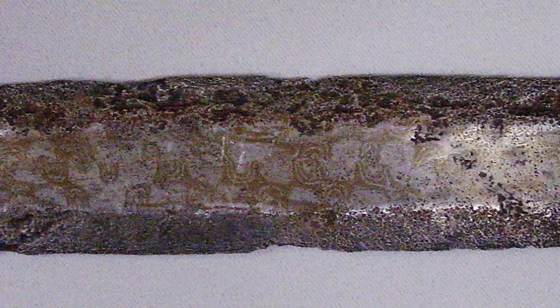It now resembles the original blade. At one point in modern times, the archaeologists must have cleaned up the blade and polished the core and etched it in acid to show the pattern. Much of that work remains visible, although it does get washed out towards the tip of the blade. You can see that the checkers pattern is made of 2 bars and that the grinding was a bit off-centered, like we had mentioned before.